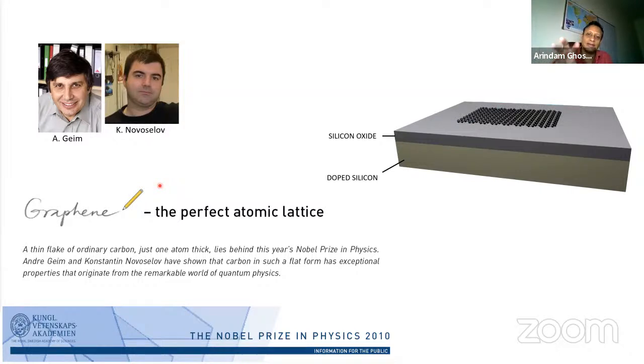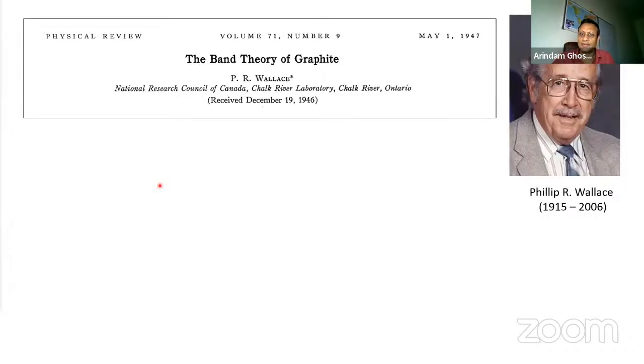What turns out is that it leaves graphene, individual layers of graphene, with some probability on the surface, and then they put electrical contacts, leading to a field effect transistor, which led to a lot of very interesting electrical properties. So this was the start of graphene that we think of in modern day research. But the story of graphene actually started much earlier. The fact that graphene is a very interesting element started nearly in 1947, 75 years ago, when Philip Wallace, who was in Canada, a theorist, was calculating how the electrons in graphene move and their energy in a lattice of hexagonal carbon atoms.